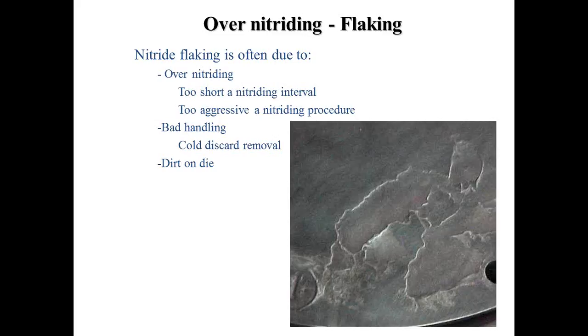This problem with flaking is often made worse by the fact that people who use baff rings wish to remove this piece of aluminum from the baff ring somewhere in the die shop prior to putting it in caustic, to try to save the amount of caustic used. If you remove that baff ring discard cold, the aluminum is sticking to the steel very, very firmly. And this can lead to making the flaking problems worse.